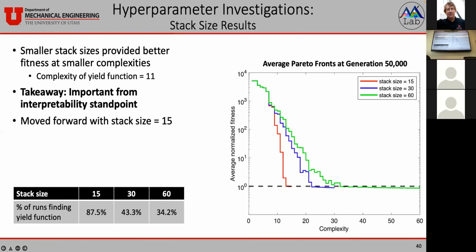On the bottom left here, I'm showing the percentage of runs that found the yield function. We can see using the stack size of 15, we were almost 3 times more likely to recover the yield function than using the larger stack sizes. And so for these reasons, we moved forward with the stack size of 15.